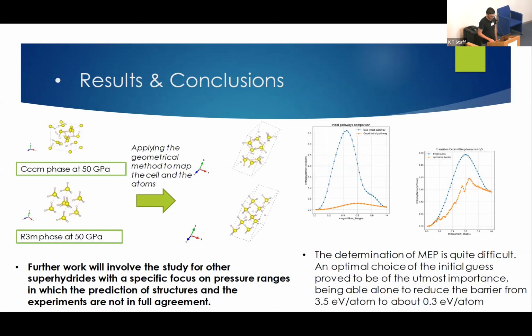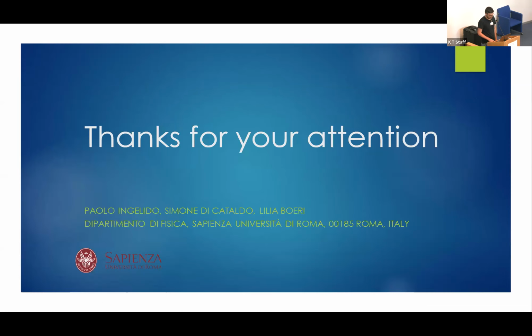And I want to show you that an optimal choice of the initial guess, so applying this mapping, reduces the barrier from 3.5 electron volt per atom to 0.3. And this is the first step to obtain a good initial guess, and so the real minimum energy path. And for this reason, we are interested in other superhydrides, especially where there is a mismatch between experiments and predicted results. Thank you for your attention, and see you tomorrow at the poster session.